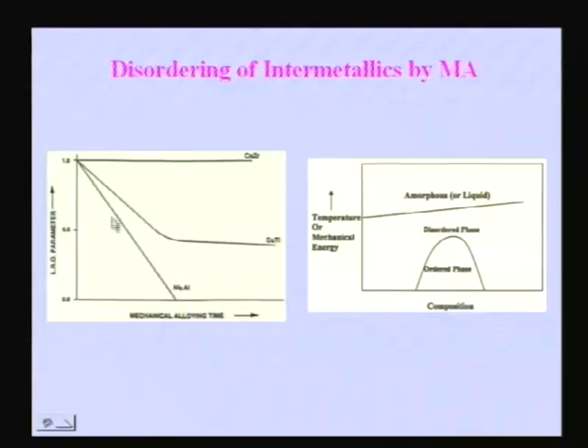So, if you look at it here, this is one example, Ni3Al, copper titanium, cobalt zirconium, 3 different ordered compounds that have been ball milled. As you are increasing the milling time, the long range order parameter decreases. In one case it continuously decreases and becomes 0, in one case it decreases and more or less reaches a saturation, below that it does not decrease much, and in one case it does not decrease at all, because this is a very strong ordered compound. So, it is very difficult to introduce disorder into some strong ordered compounds. NiAl is one such compound. Ni3Al can be made very easily disordered, but NiAl cannot be made disordered.